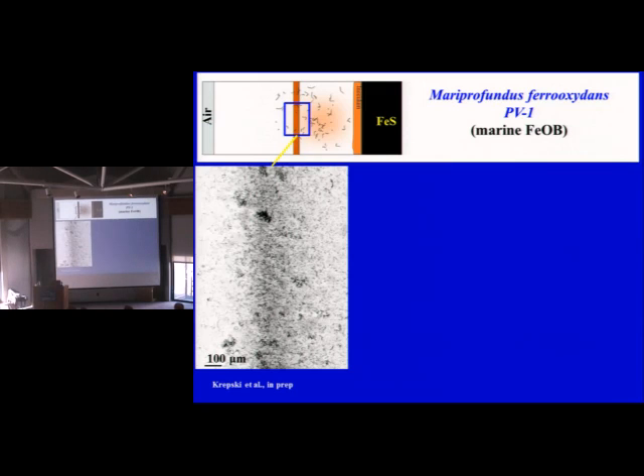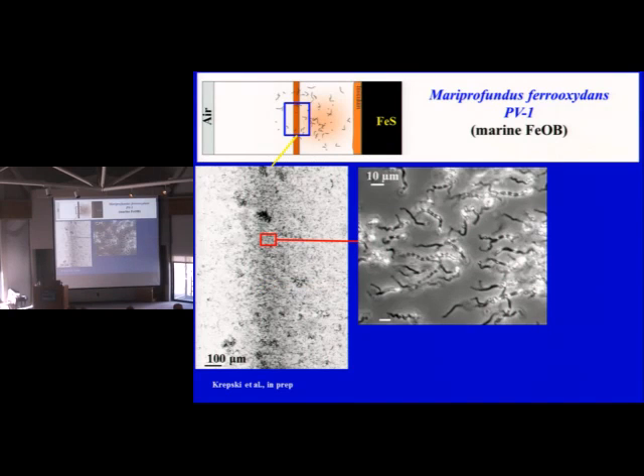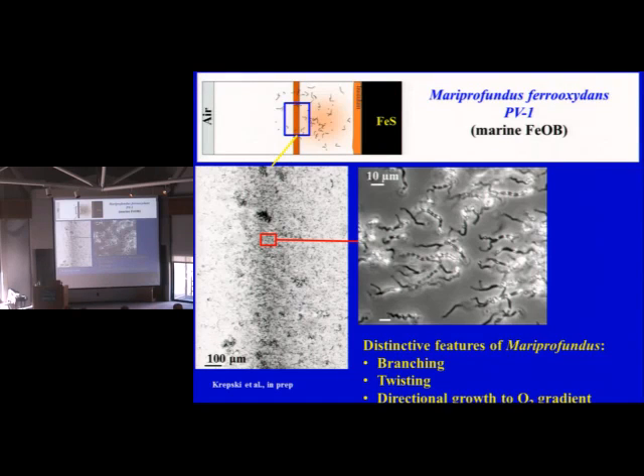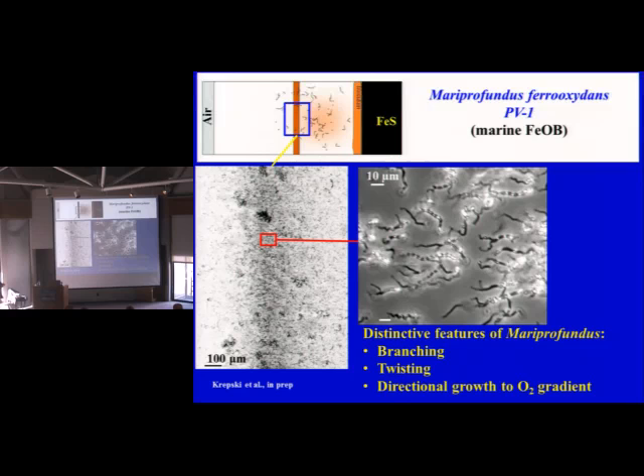But here's an example of some interesting things about the morphology, which Sean has spent a lot of time doing. So here's your band. He's going to look at how these little pieces of precipitate line up. So what he's done is this. Here's a section here of about 10 micrometers. And you'll notice that there's an awful lot of directionality. They sort of look like they're going horizontal, don't they? So we see distinctive features. We'll see some branching. Here's some branching. You'll see twisting. And the directional growth is towards the oxygen gradient.